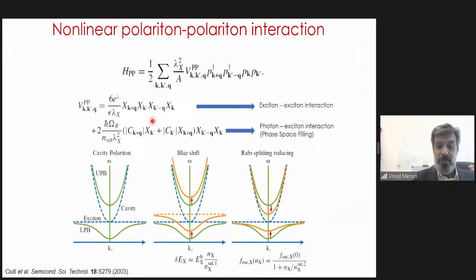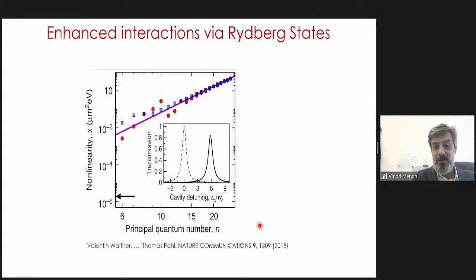Now, for those really interested in the details, I told you the penalty that you pay is because of the polariton interaction. Now, the polariton interaction arises due to two different causes. One is the exciton interaction or the exchange interaction. The other is the phase space filling, or in other words, you don't have any more absorbers available and you just fill up the thing. So both these effects become dominant. But if you look at what the result of both these effects is, if you sit at this lower polariton, they just blue shift. Okay, and so the effect that I was telling you in the last slide essentially holds.